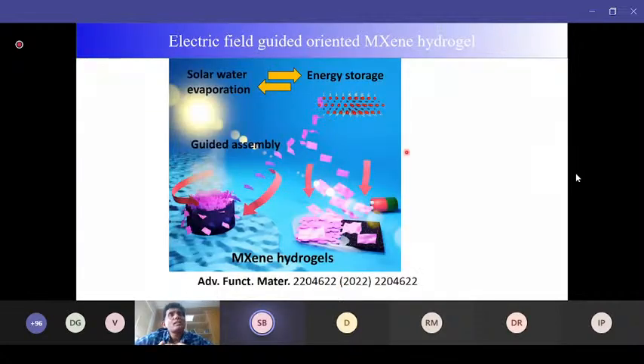And finally, this one is the last case. It is also a kind of MXene hydrogel structure, but here our target was different. We started this work with two targets. One is that the critical concentration required for this freestanding hydrogel was so high, like 50 mg per ml or 60 mg per ml. This is hard to achieve, this high concentration. Can we reduce the required critical concentration to some sufficient level, like 10 mg per ml or 15 mg per ml? This is one target. And another target was, can we control the orientation of the sheets, either in the horizontal direction or the vertical direction? So orientation control of the hydrogel is one of the focuses for this case.